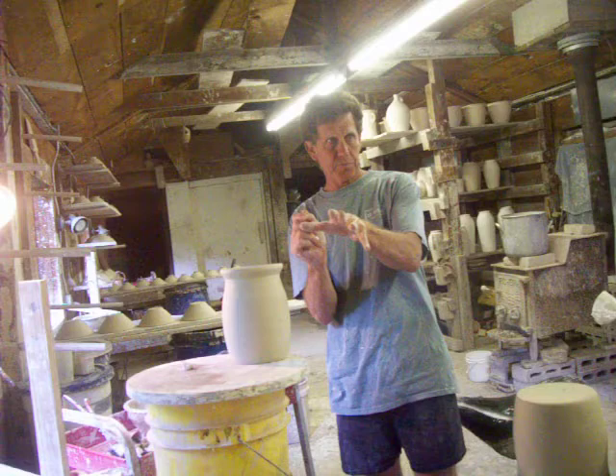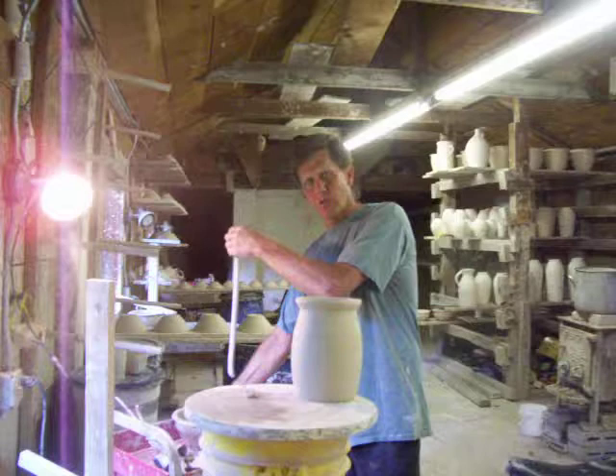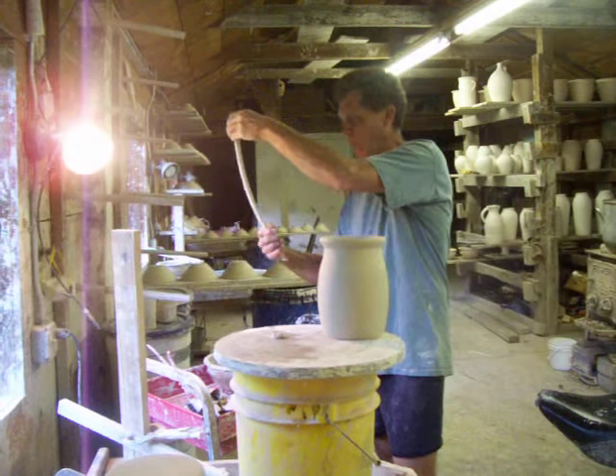So you're always pushing and pulling heat through that. How long is the kiln burn? It's about three days, cold to finish. We'll burn a small fire for about a day and a half, which is called a preheat. And then for about 20 hours we're just firing and stoking. You're monitoring this thing for 76 hours. For the first day and a half you only have to throw a piece of wood on every few hours. But when we go to what we call full fire, you're stoking every couple of minutes.